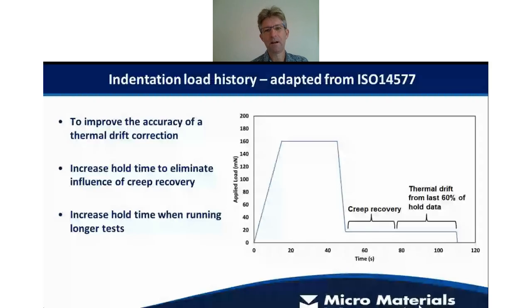So if we look at an ISO 14577 type load history for an indentation test on a metallic material, we load up, we have a hold for creep, the idea being that the creep exhausts, and then we have a relatively rapid unload, and then we have a long period at 90% unloading where we are essentially measuring thermal drift. And what the ISO standard says is that we need to ignore the creep recovery part at the beginning of this and then take thermal drift from the last proportion, typically 60% of that data. So if we have more creep at high temperature, typically we may need to extend that thermal drift period longer.